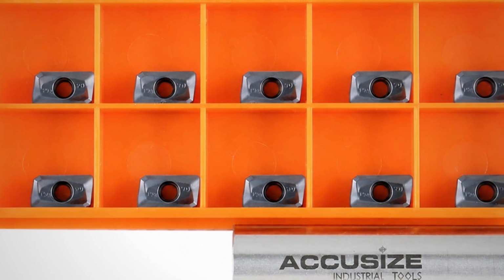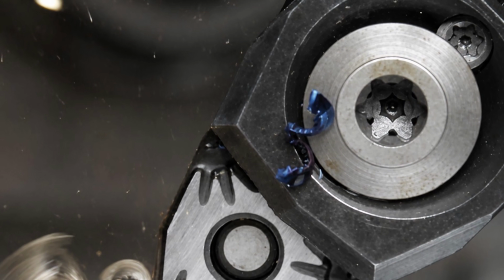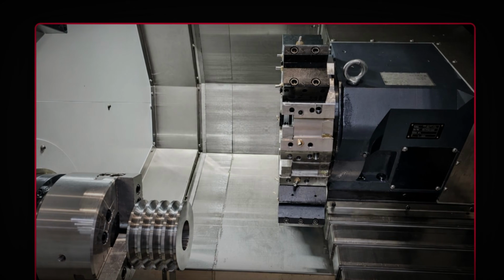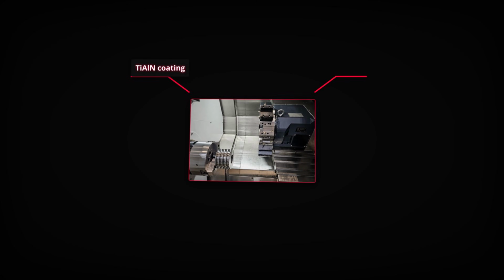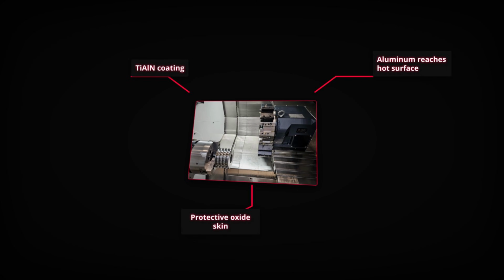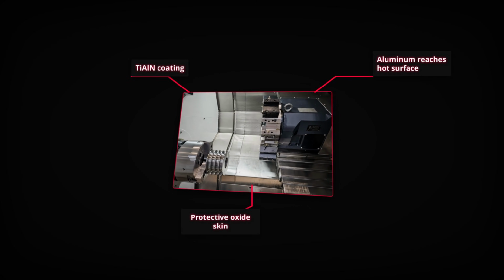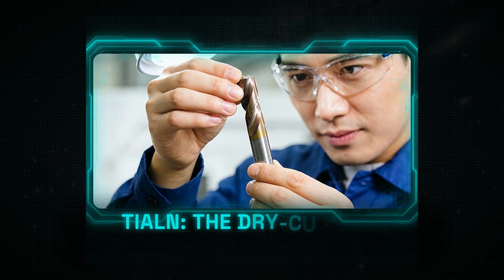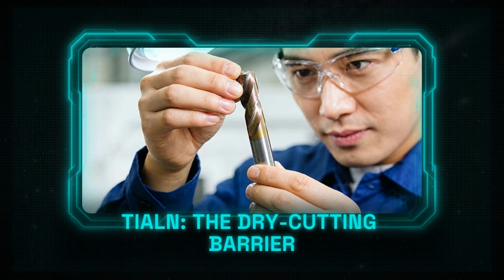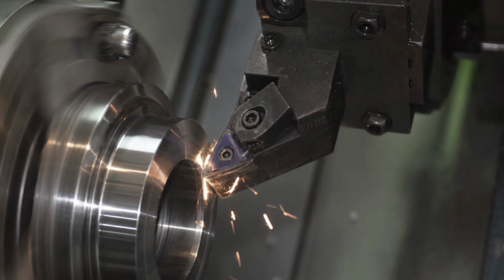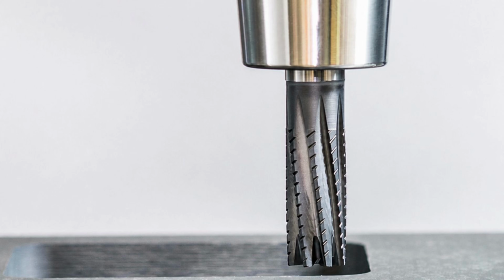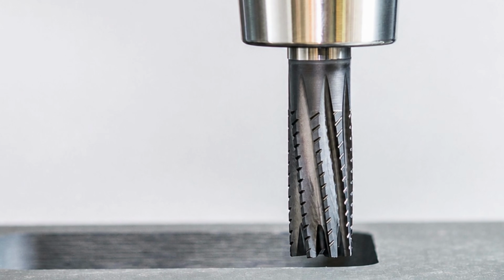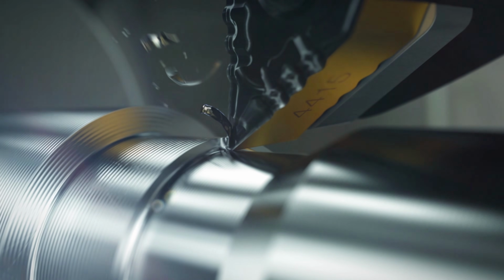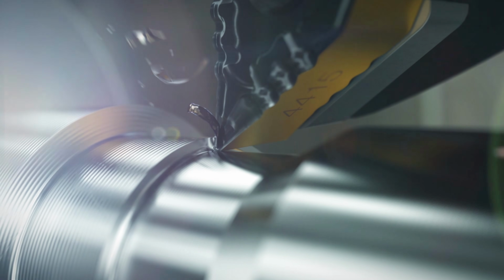Then the chemistry raced. Titanium carbonitride for wear. Titanium aluminum nitride, with aluminum that migrates to the hot surface and forms its oxide skin in the cut, the coating that made dry, high-speed machining practical. Aluminum chromium nitride for hot, hard work. Diamond films for aluminum and composites. The coated insert scaled to absurd success.